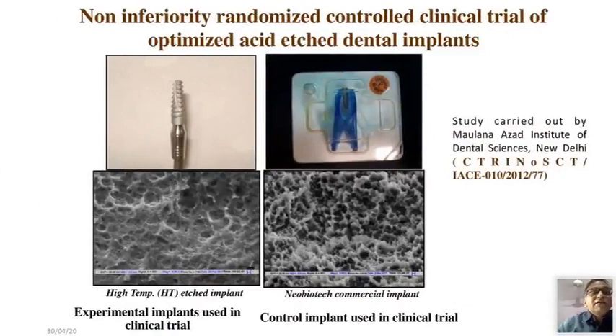So this is our IIT Delhi developed implant, which was given to Maulana Azad for clinical trials, and there was a non-inferiority randomized control trial with the optimized acid-etched dental implant. So a lot of trials have gone, and more than 200 models were made, and we have come to this microstructure which has a roughness Ra of around 1.5 to 1.8 with a honeycomb structure on the surface, so that there is a much higher bone osseointegration and the spread of the osteoblast tissues, so that they can spread out as quickly as possible, and then it becomes an osseointegrated part.